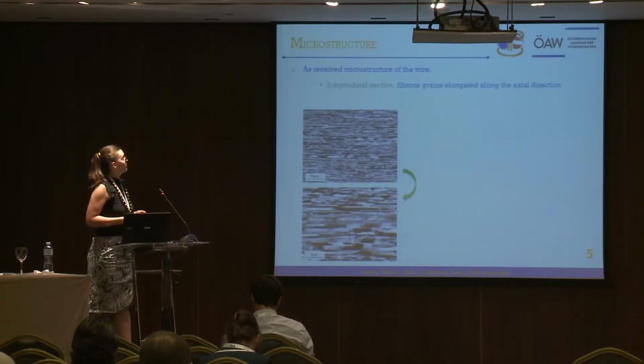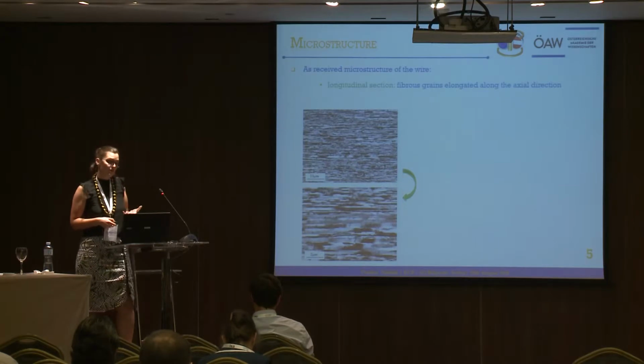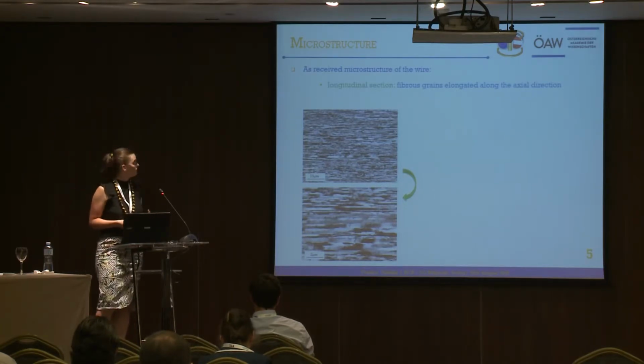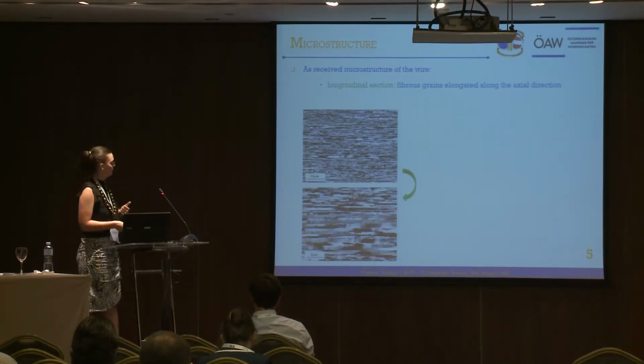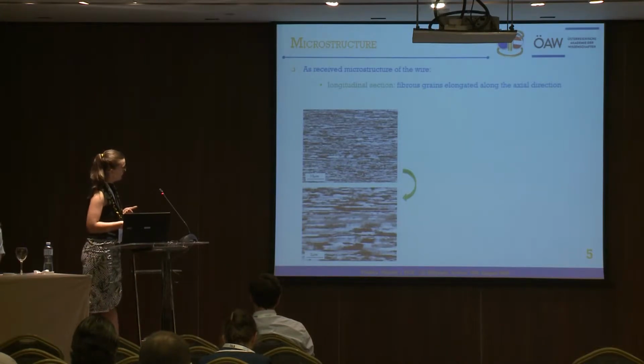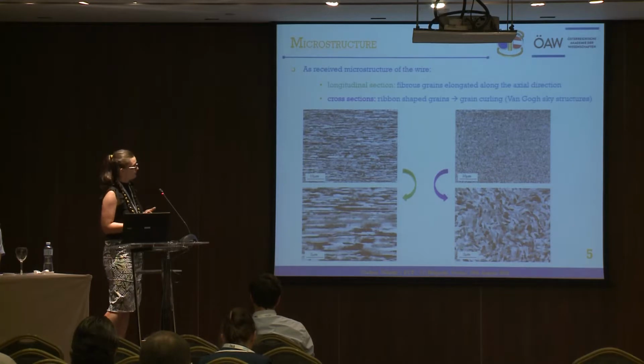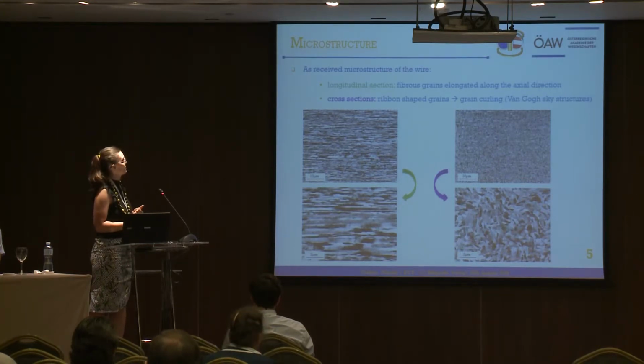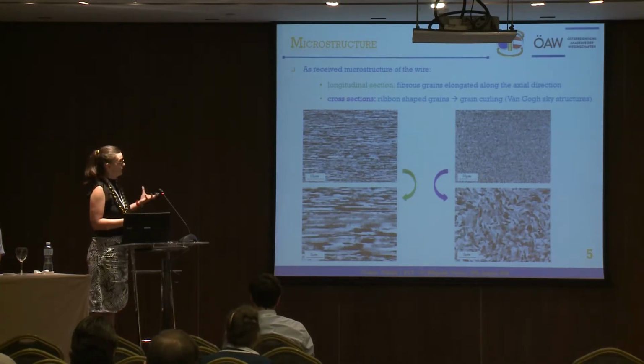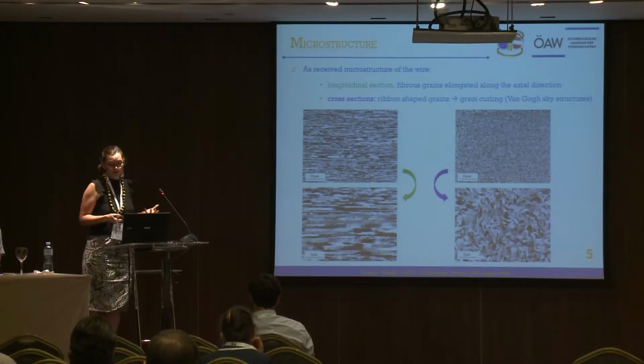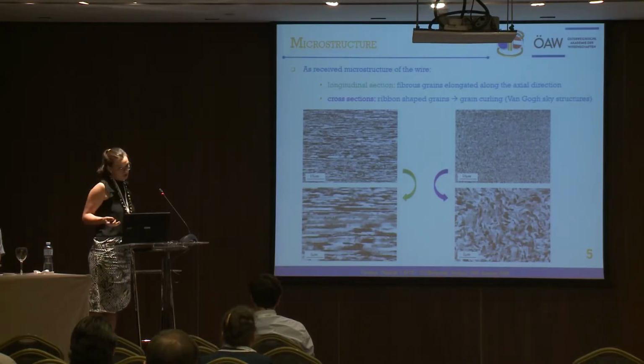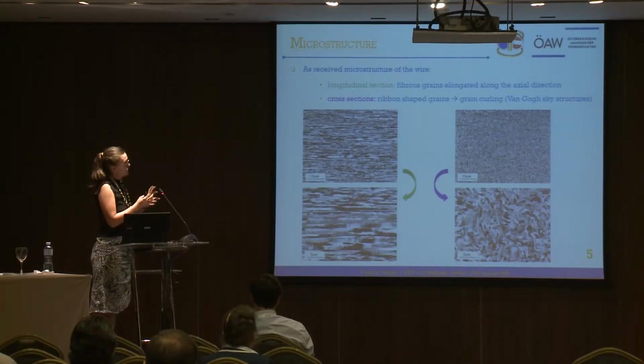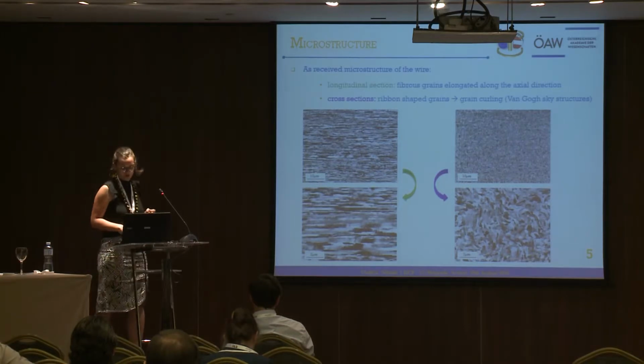So with the microstructure, as I said, it is a fibrous elongated microstructure. Here, hopefully, you see these elongated, very thin grains. And if we look at the cross-section, in the magnified picture it's seen better, the grains are curled, again as a result of the deformation process during production, and they form these ribbon-shaped structures, also known as Van Gogh sky structures.